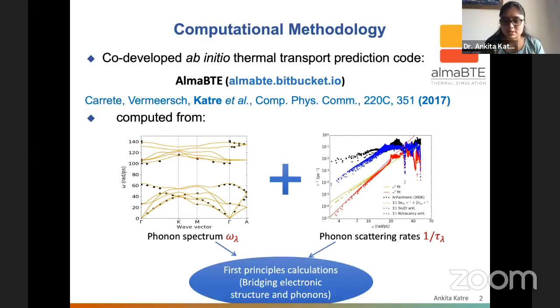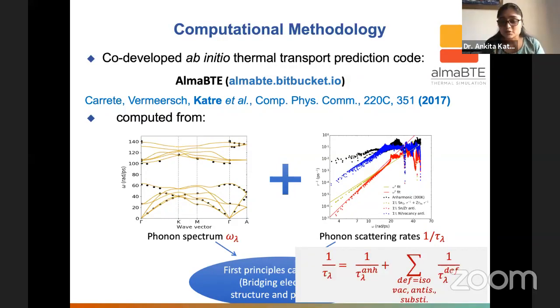Both of these quantities are calculated from first principles, from DFT calculations, bridging the electronic structure and the phonons. Coming back to the phonon scattering part: the phonon spectrum is relatively quick to calculate. If I talk about computational expense, the phonon scattering is quite heavy and extensive also because it has different contributions. We have to take care of different contributions in the phonon scattering to eventually predict the correct thermal conductivity.